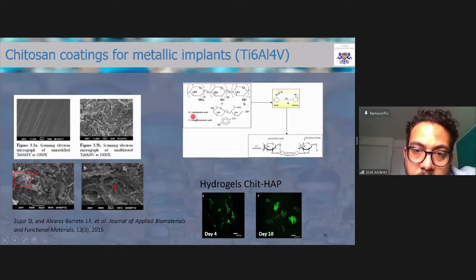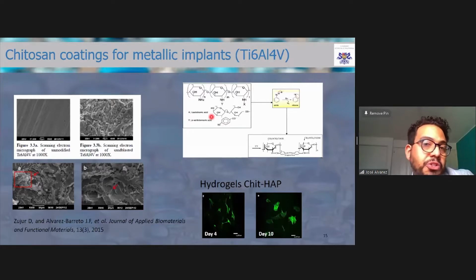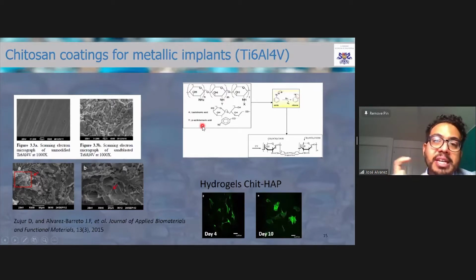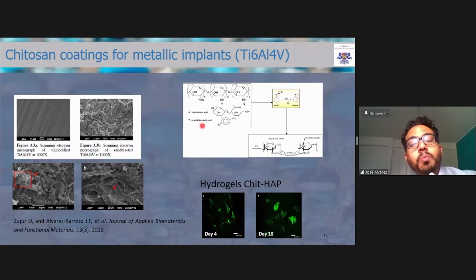One is creating a chitosan lactide, and the lactide will make it soluble at physiological pH, which is between 7.2 and 7.4. And also we put these azide groups that make them cross-linkable under UV light. So if you have a solution of this modified chitosan under UV light, it would create a hydrogel.